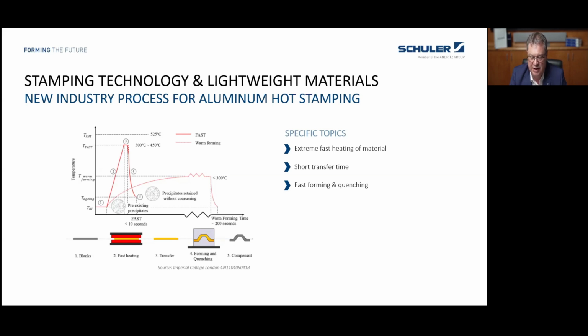And the end result was that heating by contact between two heated plates is the only way that you can heat up the material in the time you need to keep the precipitates in the microstructure of the aluminum. So you can see here on the graph that you have a very fast heating up to about 300 or 450 degrees Celsius. And then you need a very, very short and fast transfer from the furnace or from the heating station into the forming die. And then you do the forming and quenching.